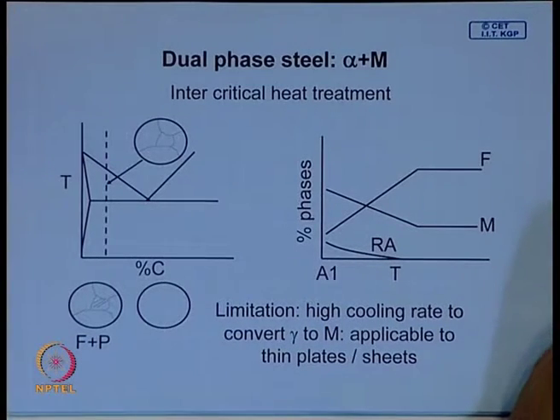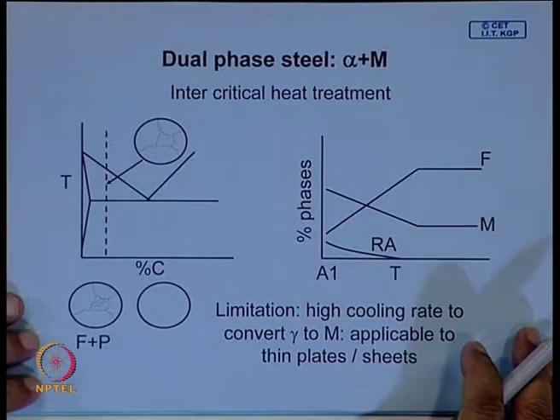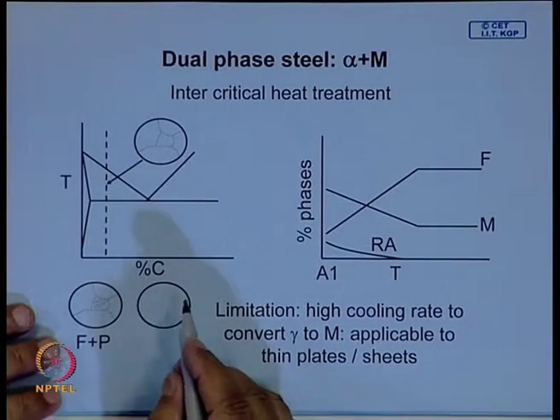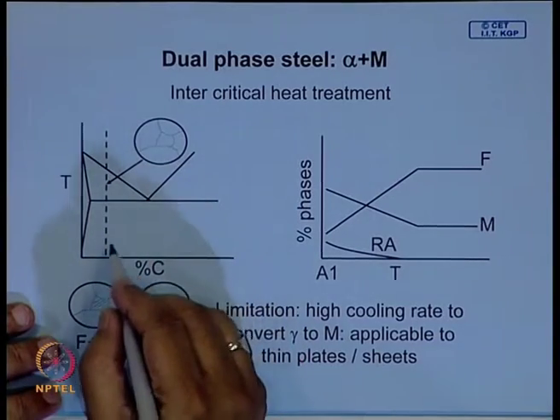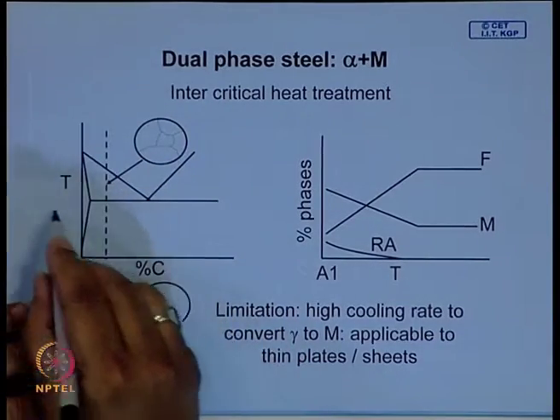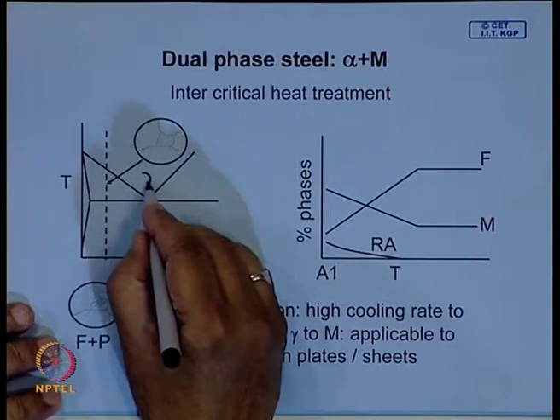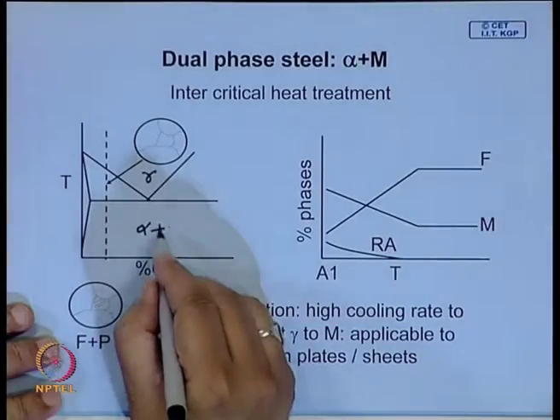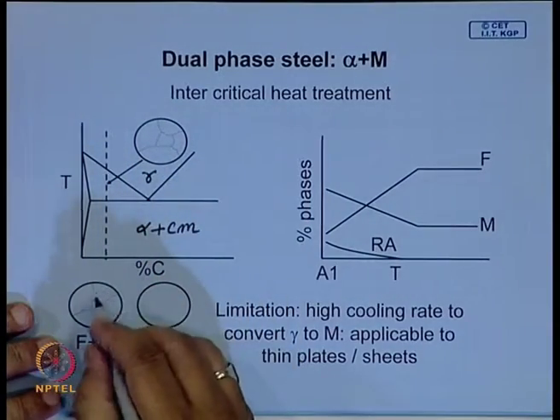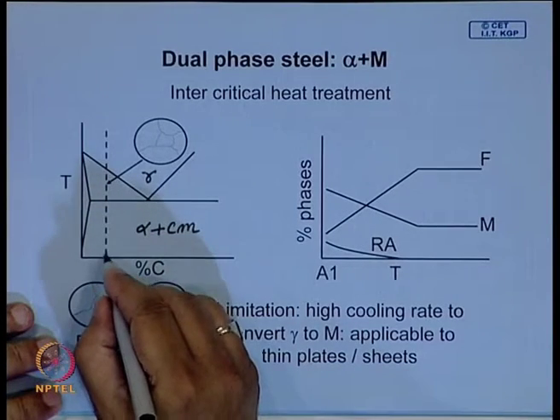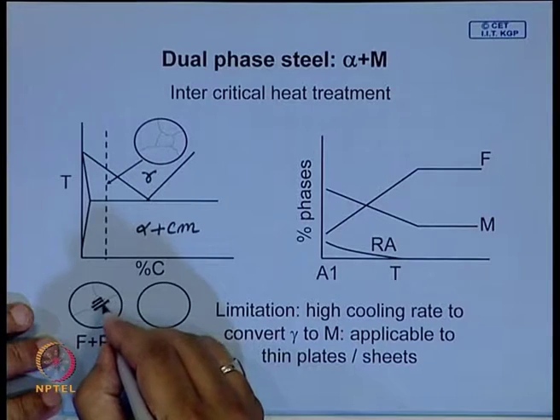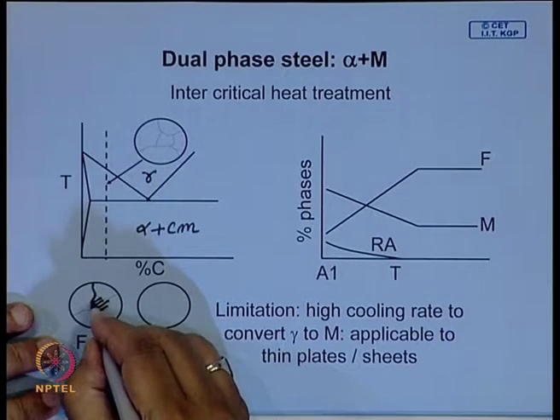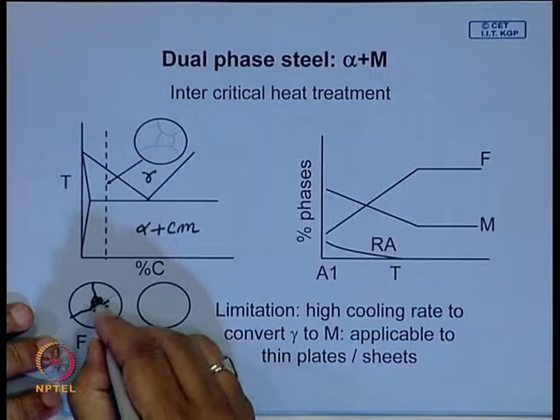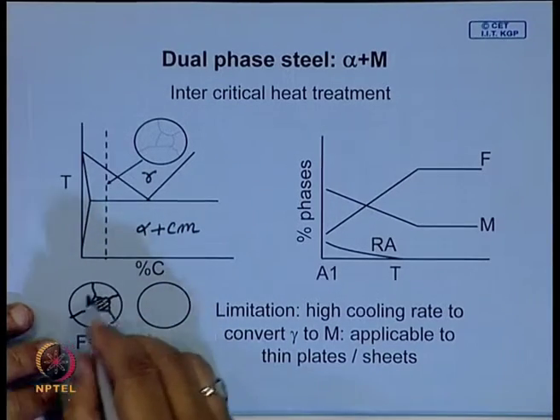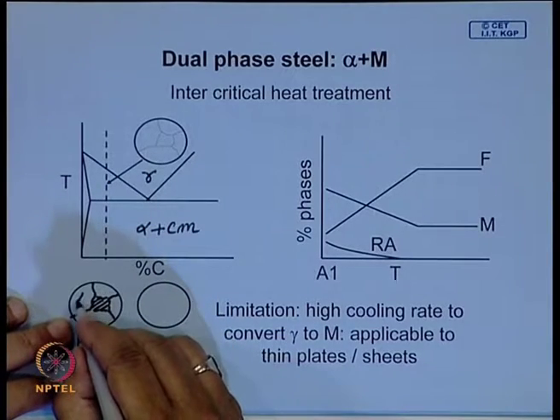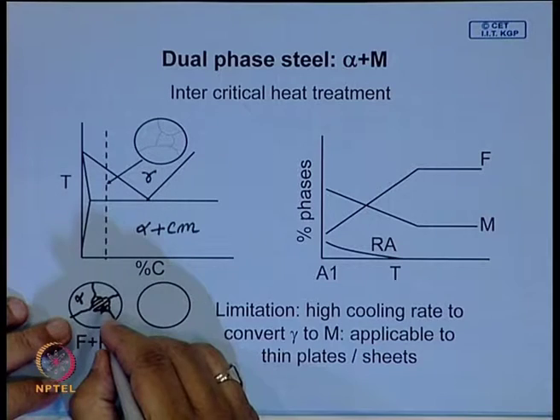Now, let us talk about dual phase steel. In a dual phase steel, what we do is a normal heat treatment process. Suppose this is the composition of steel, this is the part of the iron carbon diagram, this is austenite, and this is the ferrite plus cementite region. So, the normal structure is something like this. Of this particular composition, you will have pearlitic regions and you will have ferrite grains. So, it is made up of two distinct regions: the primary ferrite and the pearlite.